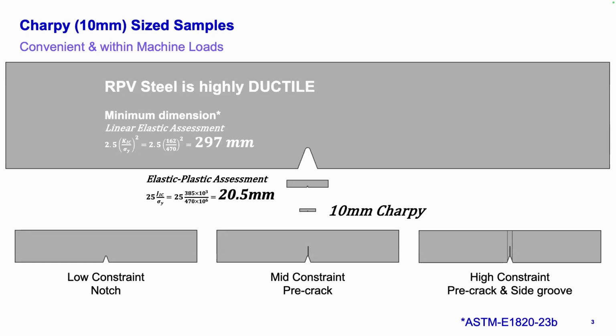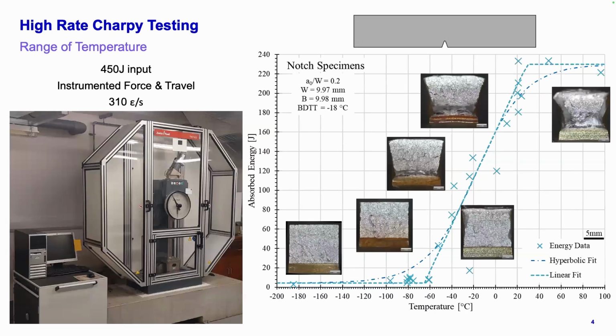The key areas that I've done so far then is Charpy impact testing. So that's a high rate test. And the best sort of results I can show you are the energy requirements. So I have here absorbed energy for fracture. Very nice curve that we're getting with our very nice Charpy machine. It's an instrumented Charpy machine. So not only can I observe the energy required, I can also investigate the force and displacement histories from each of these impacts. So from a number of tests, we have the lovely traditional sort of Charpy test transition curve